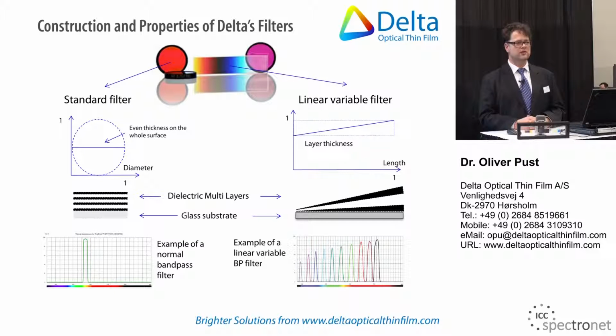This slide shows the principal difference between a classical filter and a linear variable filter. On the left-hand side you can see how on a glass substrate the dielectric multilayers are coated, and the aim of course with a classical filter is to have the coating thickness as uniform as possible across the whole batch of filters. If that layer stack represents a bandpass filter, we get one center wavelength and one bandwidth across the whole filter. What we now do with our LVF is to modify the deposition rate in the coating chamber in such a way that we get a linear gradient across one dimension of the substrate.